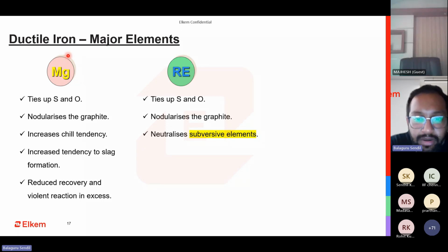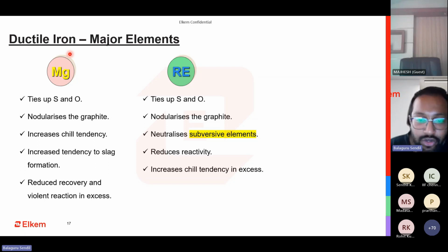There are a lot of other subversive elements that can be in your chemistry, but those will not directly impact the shape and size of your graphite. But there are some elements which will impact it. To neutralize all those elements, rare earth can be useful. This rare earth can go tie up all these elements. All these subversive elements, if you categorize them, are slightly on the heavier side. Rare earth can tie with them and form stable compounds which will go into the solution. It will not come out separately. And it also makes your reactions a bit calmer. A calmer reaction is always better. It also increases the chill tendency.